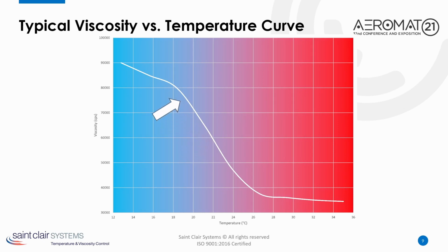Here, we can see that the viscosity falls from more than 80,000 centipoise to less than 40,000 centipoise. That's a 2-to-1 shift in viscosity over less than 8 degrees C. From this, it's easy to understand that small variations in temperature will produce large changes in viscosity, which will significantly impact the performance of the process.